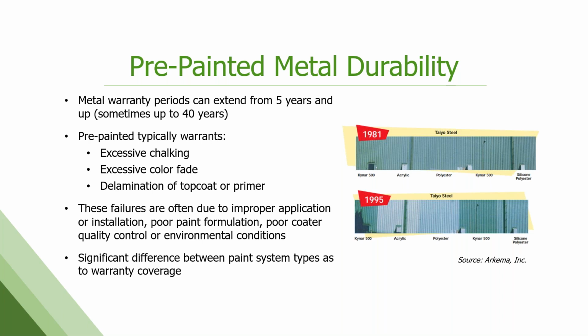In some cases, it's going to warrant against excessive chalking, excessive color fade, and delamination or failure of the top coat or primer to the substrate. These failures can occur for a lot of reasons. It could be due to improper application or installation. It could be a bad paint formula. It could be that me, the coater, didn't apply the paint correctly and meet the right specs. It could be due to the environmental conditions the coating's been exposed to after installation.